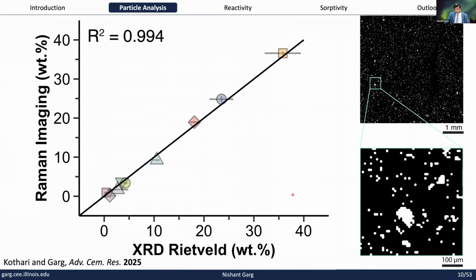So we did this on a couple of different systems. This was some work done on a calcium sulfoaluminate system. Again, we get a very decent agreement between the two techniques. And in fact, what we find is that the Rietveld also has some intrinsic uncertainty, and Raman also has that. When you combine them together, they can be really beneficial to each other, because the strengths of one can be paired with the weaknesses of the other, and together they can increase our confidence in whatever we are quantifying in a given mixture.